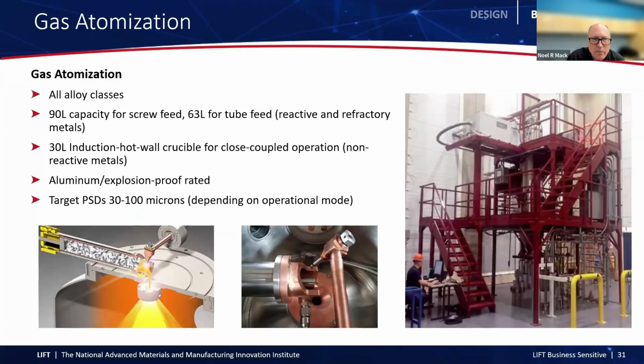On the atomizing side, it can be run again in multiple modes, roughly 90 liter capacity for the screw feed or 60 odd for the tube feed. And then we can also run an induction hot wall crucible for a close coupled operation, which is for non-reactive materials. This equipment that you see in the picture stands roughly 26 foot high, so pretty much fills the high bay to the ceiling.